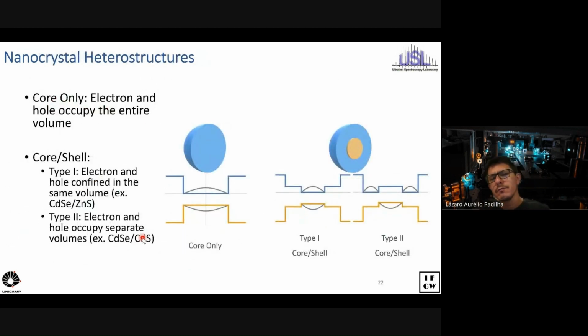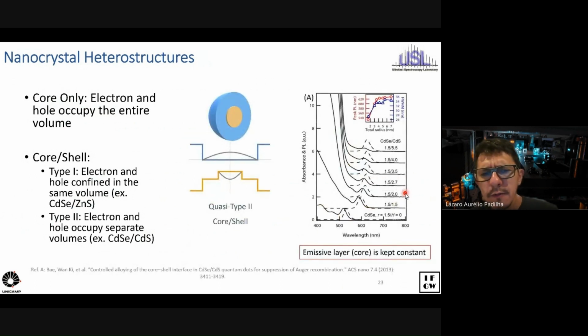So one way to try to manipulate the two-photon absorption response without playing around with the emission would be to explore heterostructures. So here we explored, for example, core-only, cadmium-based core-only, and two types of core-shell. Type 1, which is cadmium selenide zinc sulfide, where the electron and holes are confined to the core, and the quasi-type 2, not quite type 2. Type 2 is when electrons are on the shell and the holes are on the core, for example. But the quasi-type 2 is when holes are on the core and the electrons are on the whole core and shell.